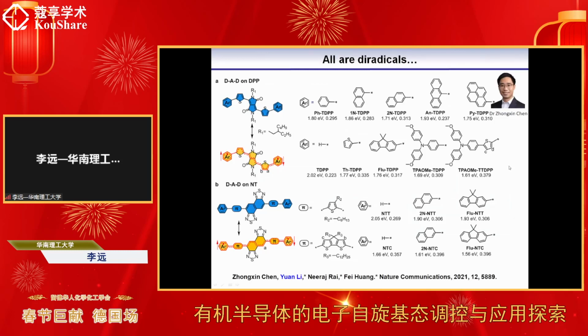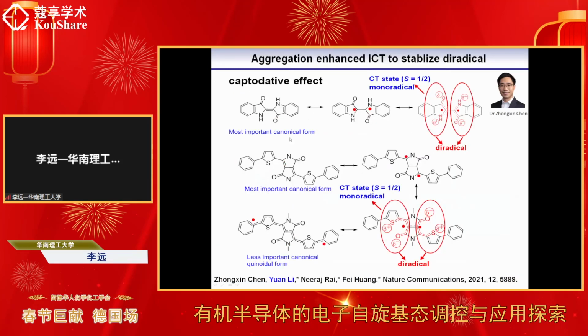We found all of them are radicals, and they all show the ESR spectrum. And this is a mechanism. We propose aggregation enhanced ICT to stabilize the radicals. You can see there are two ICT processes in this compound, and finally we will get the open shell radical resonance structure. And this is the aggregation-induced radical experiment. We showed that aggregation played a very key factor to stabilize the radical.